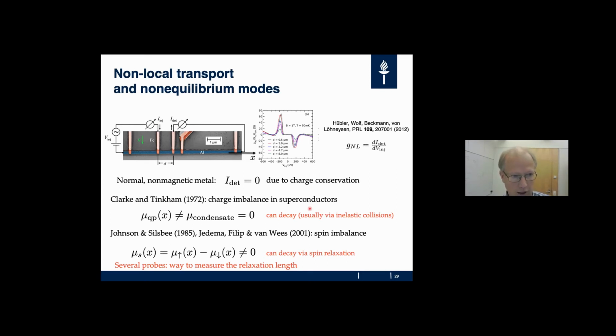Now, a similar setting was discussed in the context of spintronics by Johnson and Silsbee in the 1980s, and we heard yesterday also examples of this case where you can study the spin accumulation in this system, which can decay via spin relaxation. Then if you place these contacts at multiple locations, you can also measure the spin relaxation length.